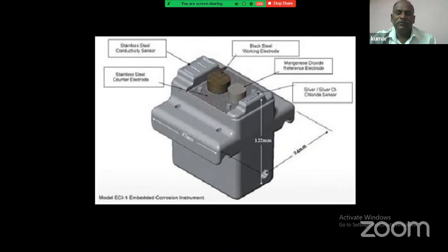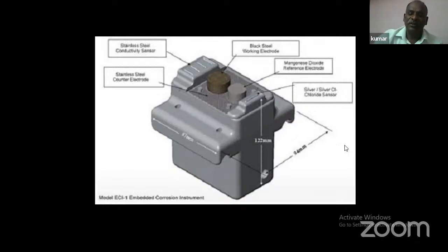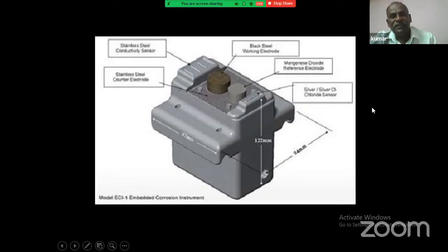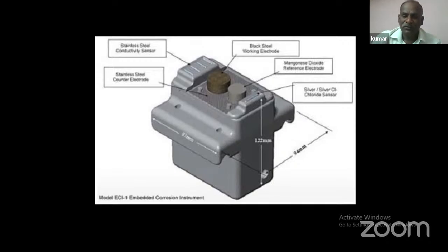Nowadays these kinds of corrosion measurement sensors are available, which are imported. During construction you can embed these sensors inside the concrete, and then take the signal leads outside, and continuously it can be measured. So whether your structure is corroded or not, you can identify by using this. Instead of this, we ourselves prepared the same kind of sensors, which we can use very easily.